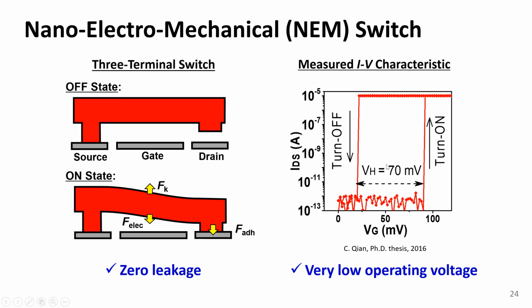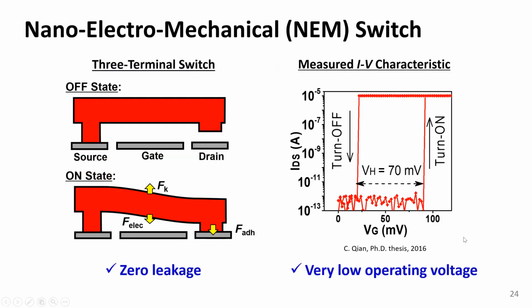Now, such low hysteresis voltages are achieved through materials engineering. So that's pretty straightforward. And I forgot to mention, even if you have small variations in the turn-on voltage and turn-off voltage, as long as both of these voltages are greater than zero, you will always have zero off-state leakage. So that eliminates the problem of variable off-state leakage with varying turn-on voltages that is seen for transistors.